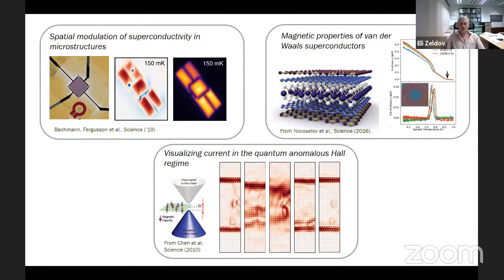What sort of currents do you drive in this experiment? We vary the current, but we go to currents as low as 5 nanoamps. I think the images that I show are typically at about 20 nanoamps, but we verify in the quantized regime that if we go to lower and lower current, and the limit there is really 5 nanoamps, nothing, at least qualitatively, changes in the images. And 5 nanoamps is a typical current also for the transport measurements. We also see in transport that once we're below 25 nanoamps, the transport is linear and the plateau well defined.